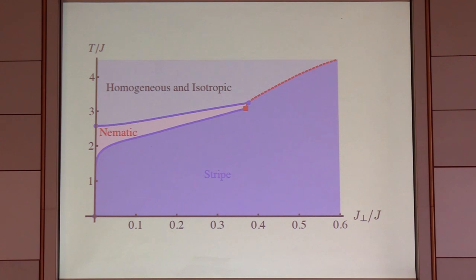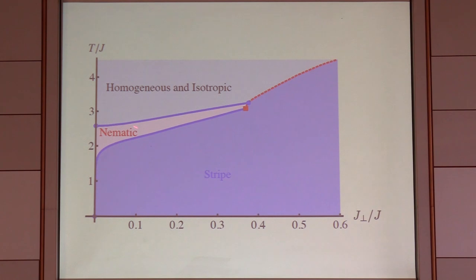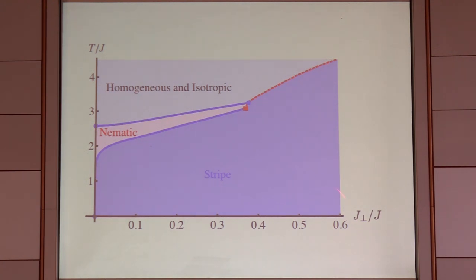Here's the phase diagram we get: temperature versus the three-dimensional coupling, more or less like the previous phase diagram. You may notice there is a very narrow vestigial nematic phase — the only reason you see it is because we've cheated; it's actually much narrower than that — and it goes away at some critical value of the interplane coupling.